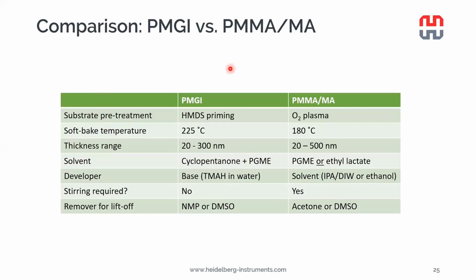Very quickly, a comparison of the properties of these two different materials. They have some small but important differences. So as I already mentioned, for PMGI it would be better to use a hydrophobic substrate, so ideally HMDS priming is recommended. While the PMMA MA likes to stick on hydrophilic substrates, so ideally oxygen plasma. But if your sample has sensitive materials, typically just native oxide on silicon is hydrophilic, and we don't have big issues with adhesion of PMMA MA.